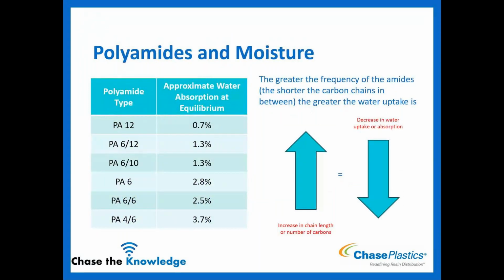Okay, so nylons and moisture. Going back to the page before, the greater the frequency of the amide groups, again, the amine and the acid groups together create an amide group, so the more often that they occur, meaning the shorter portions of carbon that exist, or the lower number of nylon it is, the greater the water uptake is. And the reverse side would be, as I increase the chain length, so there's more carbons in it, so 12 versus a 6, you end up with a decrease in water absorption.